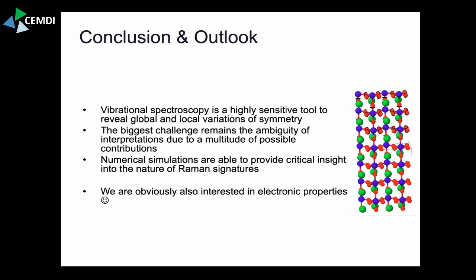So I think it depends on essentially the density of defects. If you have diluted defects, which are relatively far apart, then you can calculate your crystal and treat these isotopes as a small perturbation, and their contribution is too small to matter. Now, what is the critical length scale? It should be the phonon propagation length. If the phonon during its propagation doesn't see any isotopes, then the crystal is perfect, and you only then would have occasionally one event. But if over the propagation length of the phonon, it would see multiple isotopes, then you get this mixture. So statistically,